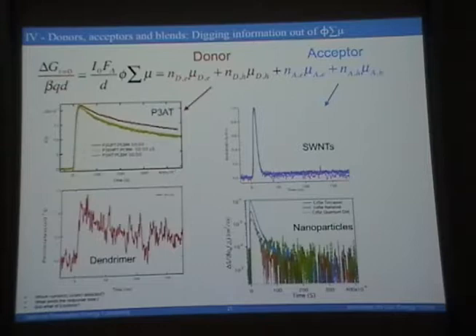So we're getting carriers in P3HT without any acceptor. The yield is about 3%. Increase the photon energy to, say, 400 nanometers instead of 600, that goes up to 89%. No acceptor. It's a really nifty idea. We should work on that a bit more. So let's excite a dendrimer. You see the signal's very noisy. That tells you that there are not many carriers produced in a neat film of a dendrimer.